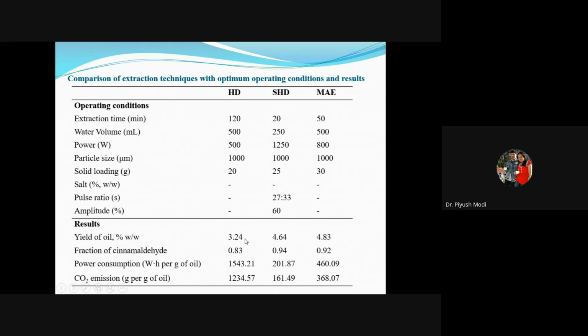Here you can see 3.24 percent yield in hydrodistillation, 4.64 percent yield in sono-hydrodistillation, and 4.83 percent in microwave-assisted. The yield is very high in microwave, but its fraction is 0.92, while in sono-hydrodistillation the fraction is 0.94, because here we use the mechanism of ultrasonic waves to rupture the plant material mechanically, whereas in microwave we use dipole moment penetration through the water, so the temperature increases. That may be the reason for the 0.02% difference, which is not notable.